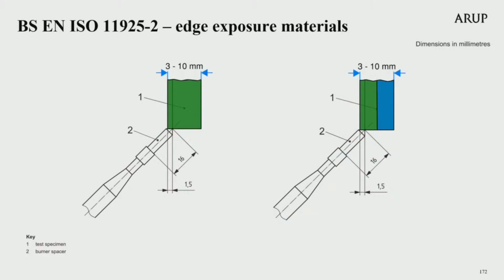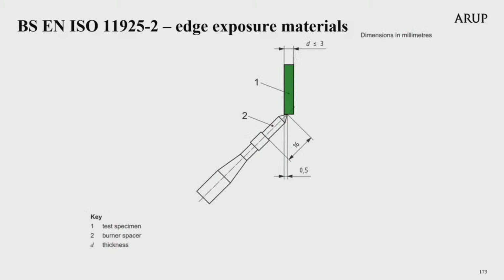For the edge exposure version of the test, the burner has specific required locations set out in the test standard. For a material greater than 3 millimetres thick but less than 10 millimetres, the flame is applied to the underside using the 45-degree angled burner 1.5 millimetres behind the front face of the specimen. This is whether it's a single layer, as shown by the image on the left, or multiple layers, as shown in the figure on the right. Where the material is less than 3 millimetres thick, the flame is applied at the midpoint of the bottom edge as shown in the test standard.